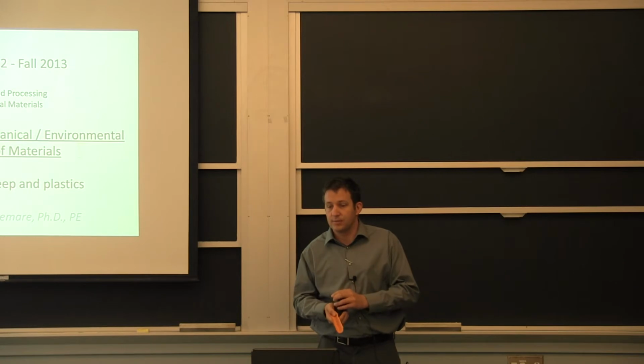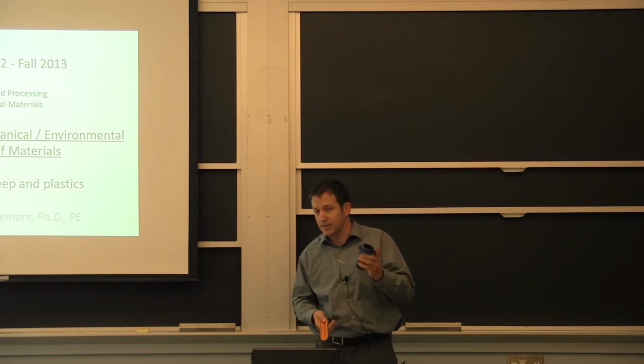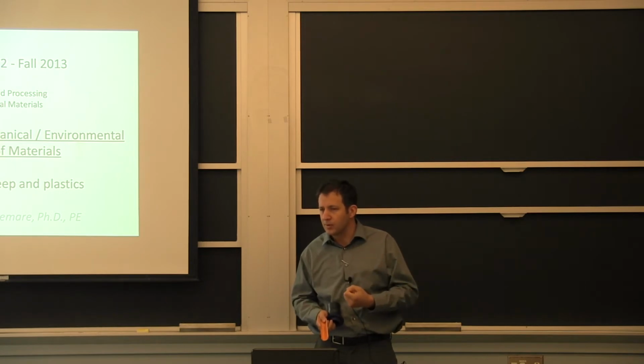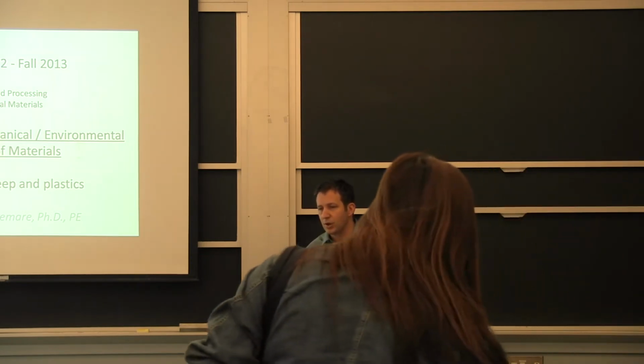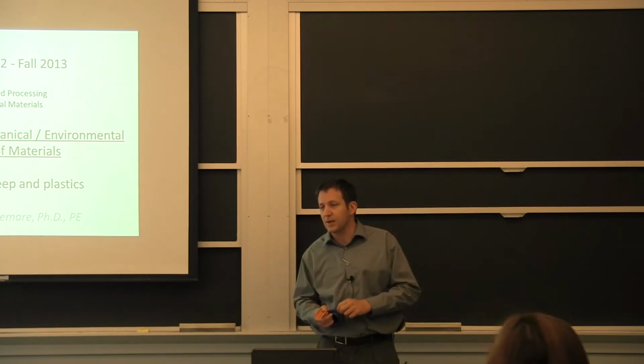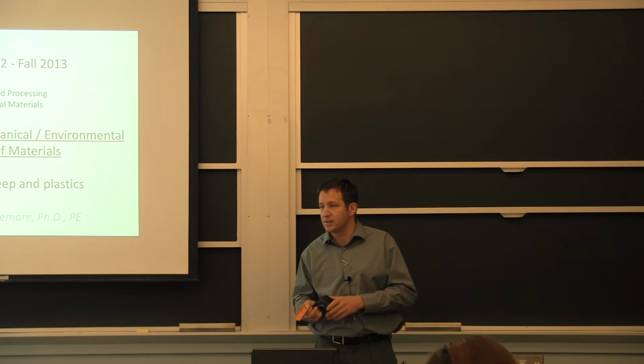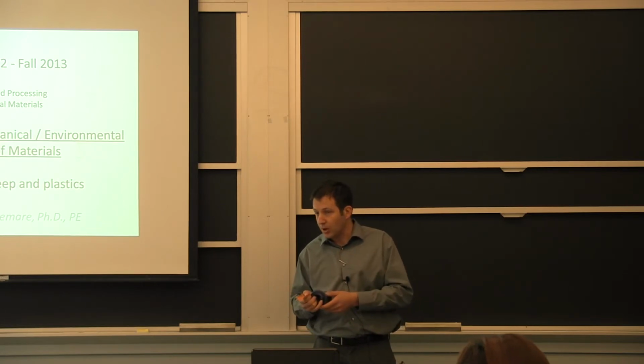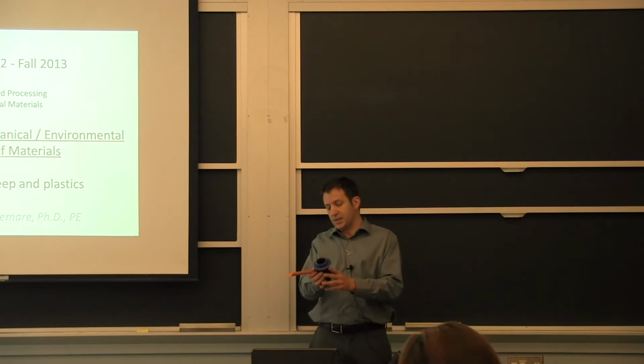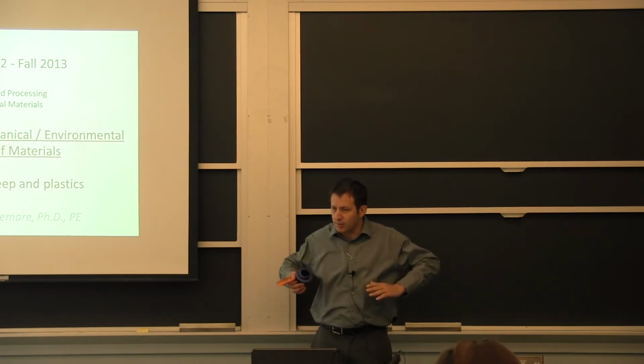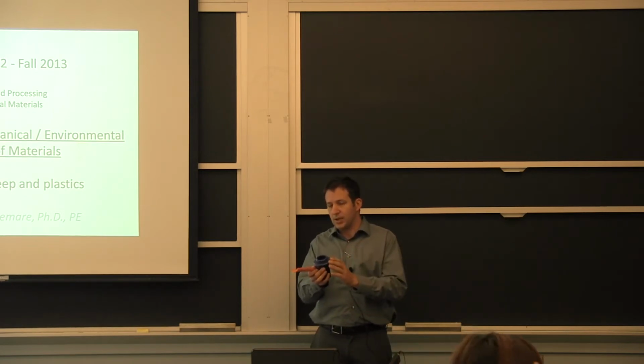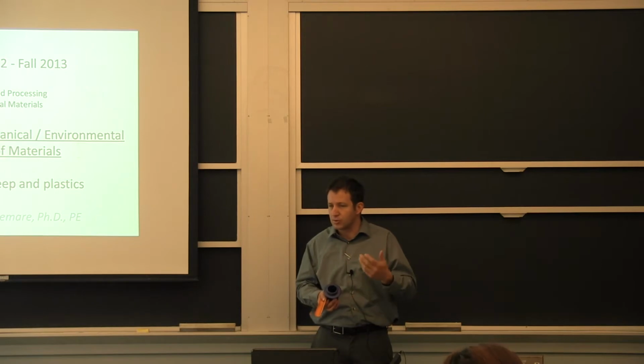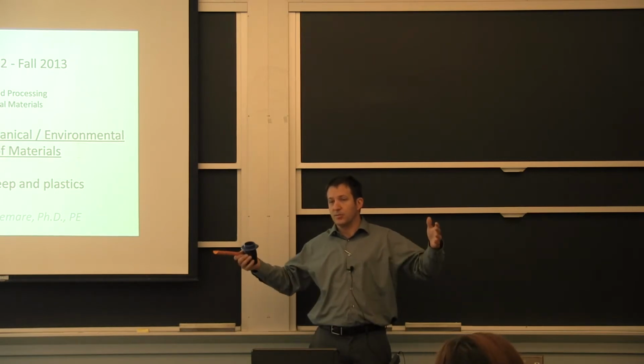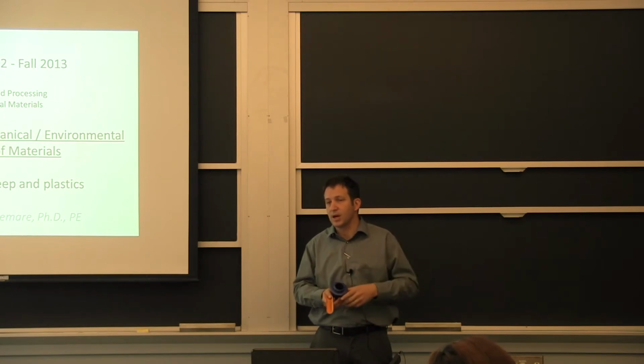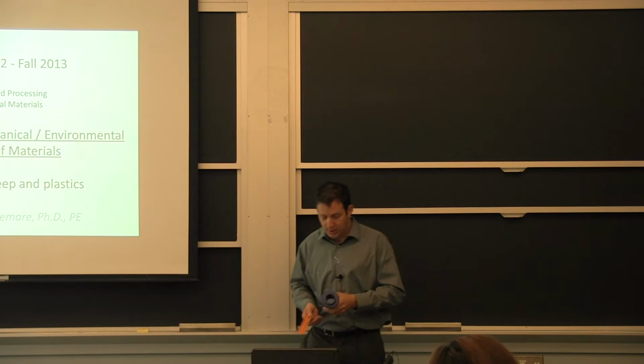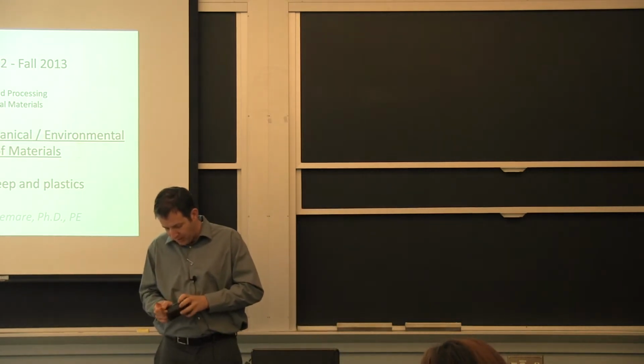And it's one of the limitations in terms of saying, I'm going to take this piece of plastic and make something very reliable. Because if you scratch it with something sharp, all of a sudden you lose the skin effect. The skin of the plastic from the molding process is typically stronger than if you machine the part. If it's injection molded, all the molecules line up, and on the surface you're going to have a kind of fiber structure, and it's going to be much better than if you take a big piece of plastic and machine it out. In that case, you have a lot of cut material on the surface as opposed to more of an arranged structure.